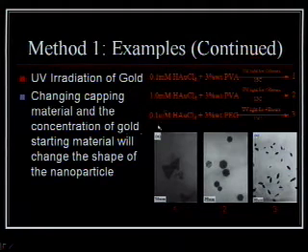So for the first one, they used a 0.1 millimolar gold solution in polyvinyl alcohol and exposed it to light to form the nanoparticles, and you got these plate-like prism structures, which you can see in the first picture. And when they increased the concentration of the gold solution to 1 millimolar, they formed these hexagonal structures, seen in 2.